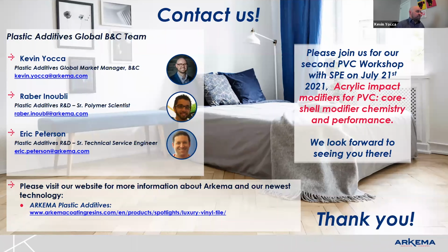When I first started in PVC, one of my first projects was to take a 2-roll mill and take temperatures every 5 degrees, and then take impact modifier at different levels and basically do a DOE and make plaques, and then make Izod bars from those plaques, and essentially make a process window for this formulation and type of impact modifier. Essentially, I could dial in that when you process at 180 and you use 4 PHR, you're going to get the best results. I could basically map the whole thing out. So that's an applications way to do the same thing that you can get from the DSC data.